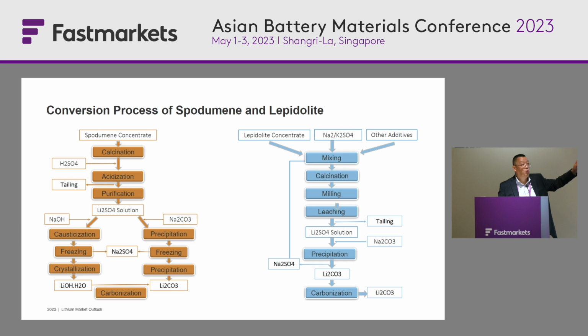Then you add the soda ash to precipitate the lithium carbonate, and you will have some residue lithium in the solution. You separate the sodium sulfate, okay, by either a hot separation or by a freezing separation, and then you will have lithium carbonate from the second precipitation and so on. And so this is how we deal with it if the purity is not good enough. So we have a typical, what we call, carbonization process, this kind of operation.